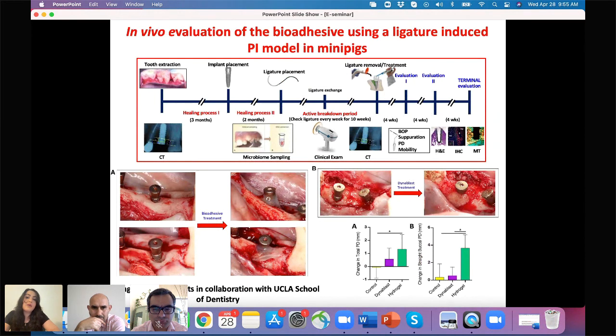So in our in vivo evaluation of this bioadhesive, our experiment was based on an induced peri-implantitis model in mini pigs, and this is a very long study. It took us a year to complete. It started by tooth extraction in mini pigs, and then we waited for 3 months for the healing process. And after 3 months, the implant was placed, and then we had 2 months of healing process after placement of the implant. Then we induced peri-implantitis by putting a ligature around the implant. And then after 10 weeks, when we observed the formation of the peri-implantitis disease, we started our treatment.